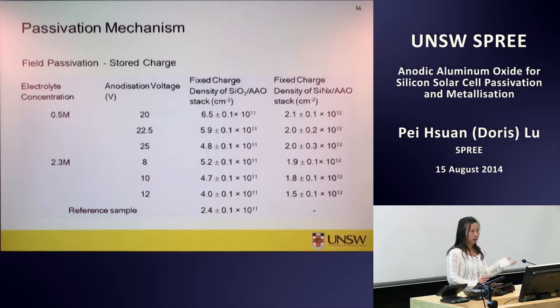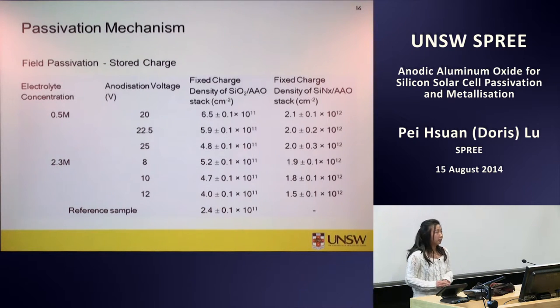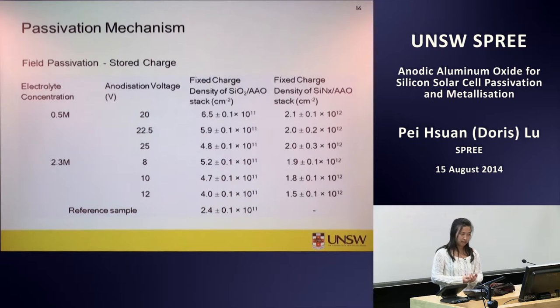So we're going to look at what mechanism allows an anodized layer of aluminium on an intervening layer to result in improved effective lifetime and implied VOC. We were looking into the stored charge within the anodic aluminium oxide, and it's interesting to see that, compared to the reference sample, an anodized layer of aluminium on top of silicon dioxide always results in higher stored charge density. However, people might wonder, if you have a 200 nanometer intervening layer, after anodizing a layer of aluminium oxide on top, the field effect induced by the stored charge might be relatively less.